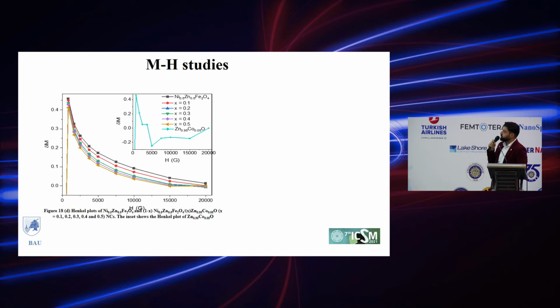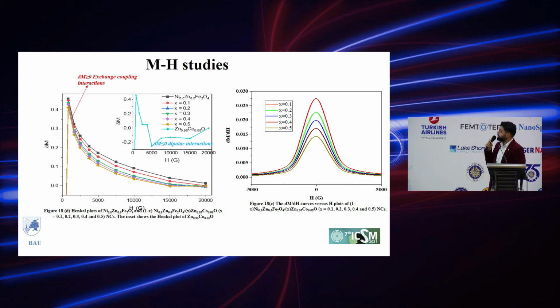Finally, in order to go deeper in the nature of exchange coupling between two nanophases, we plotted the Henkel plots to investigate the nature of the coupling interactions. And as you can see, for nickel zinc ferrite and all nanocomposites, the Henkel plots showed a positive delta M, which means the presence of exchange coupling interactions. For zinc cobalt oxide, for higher field, the delta M showed a negative value, which indicates dipolar interactions.